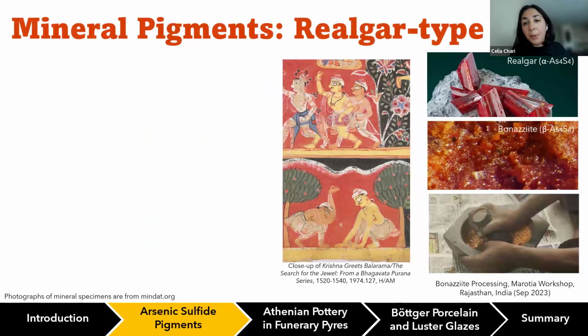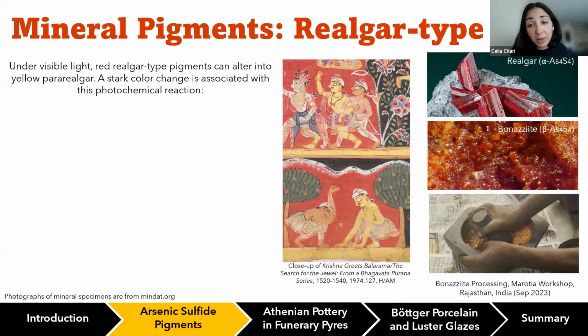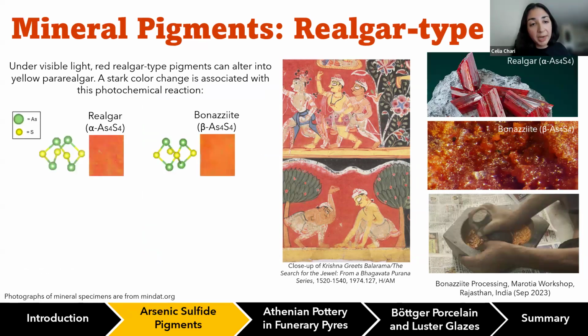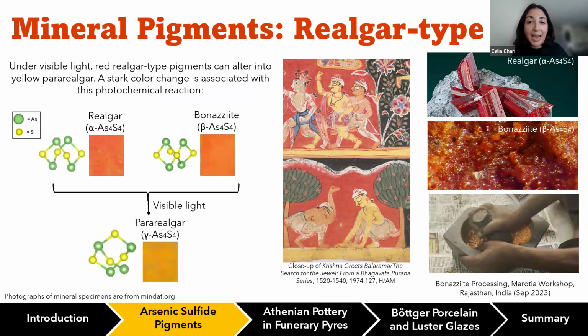One thing to note about both realgar and bonazziite is that they're really light sensitive. They can change color when they're exposed to visible light. And this is because of a photochemical reaction that takes place that alters its structure completely. So red realgar and orange bonazziite can transform into this yellow pigment when exposed to just visible light.